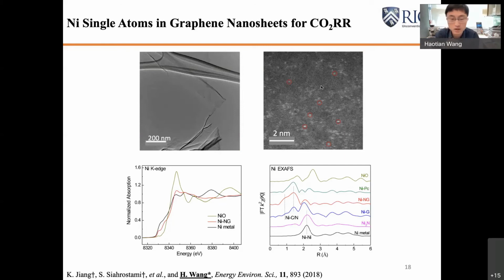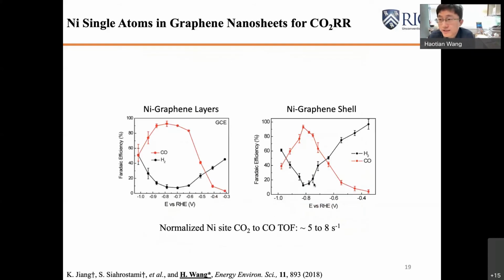its coordination structure. As you can see from here, the pre-edge actually showed us the nickel single atoms have an oxidation state that is sitting between nickel oxide and nickel metal. And if you do the Fourier transform of the extended edge, as you can see, the dominant signal now actually comes from the nickel-carbon or nickel-nitrogen coordination. There is no direct evidence that there are nickel-nickel bonds sitting there. So no nickel clusters can be seen using the XAS from these nanosheet materials. And if we test their CO2 reduction performance, this is even better than the previous version.